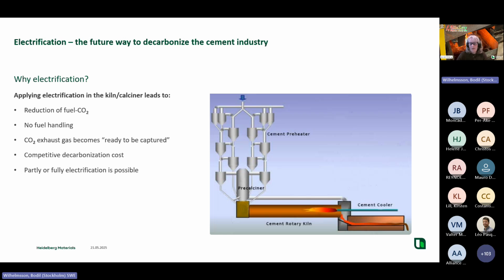Another positive effect of electrification is that our production can be divided into two parts, so to say. We have the calcination step, and then we have the even higher temperature process in the rotary kiln. Most of the CO2 and most of the energy comes from this part of the process. So if we just electrify the one part to the left, then we will achieve close to 80% of all the CO2 being separated. And if we would like to also electrify the rotary kiln, then we get 100% electrification, which could be a very nice step in the development of the electrification of the cement process.